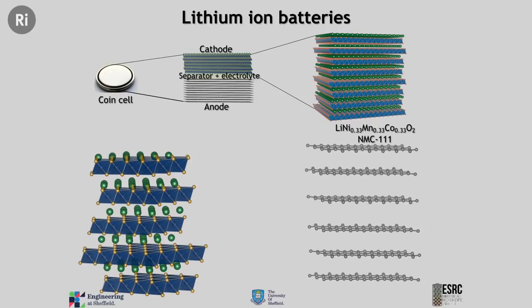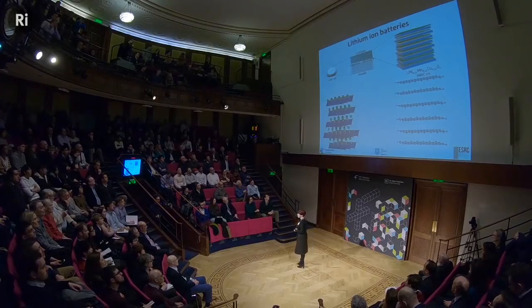So this is my NMC material. I've just blown up this structure a little bit more so you can see these layers of transition metal oxide, and these green dots here are my lithium ions. So this is my cathode material, and then on this side here, I've got my anode material, and a very typical anode material that's used in modern batteries is graphite. And graphite, again, because of that lovely layered structure, it allows the movement of lithium ions in between those layers.